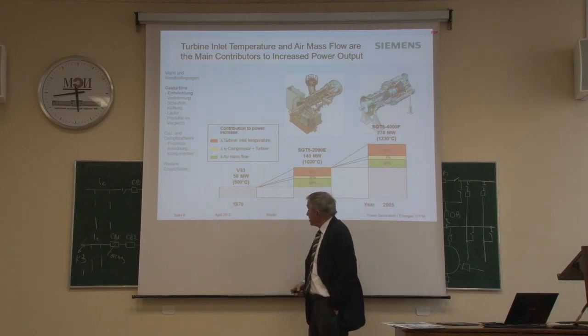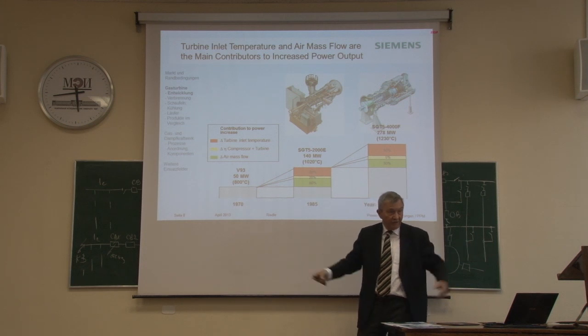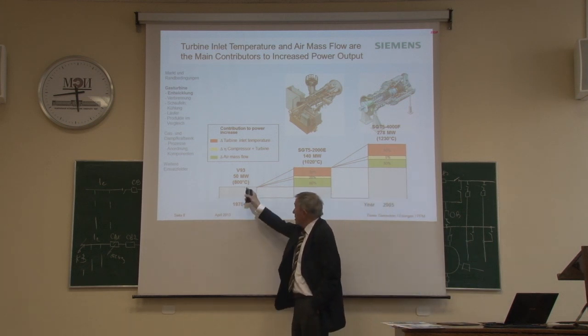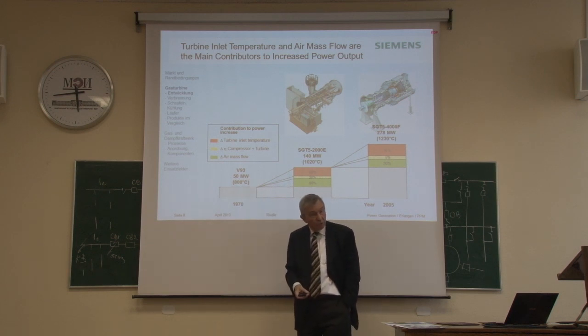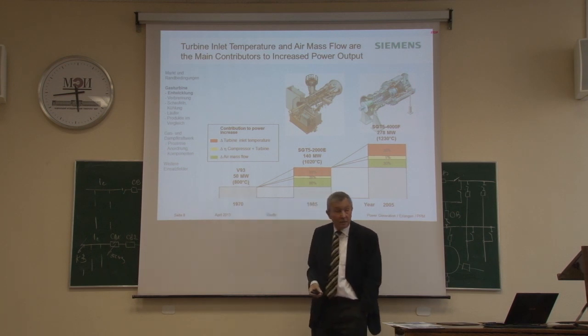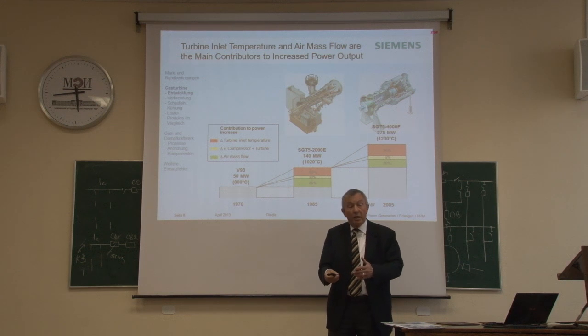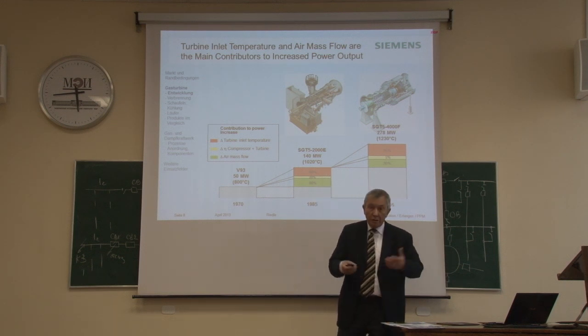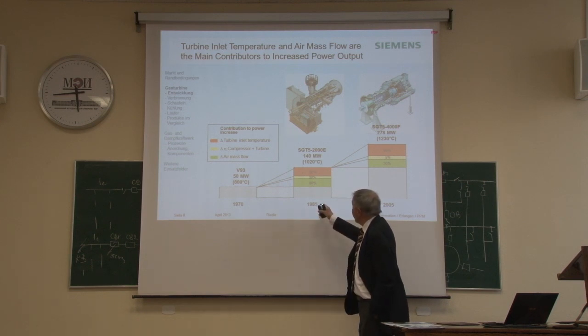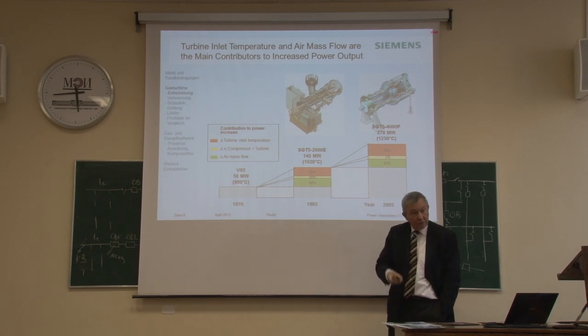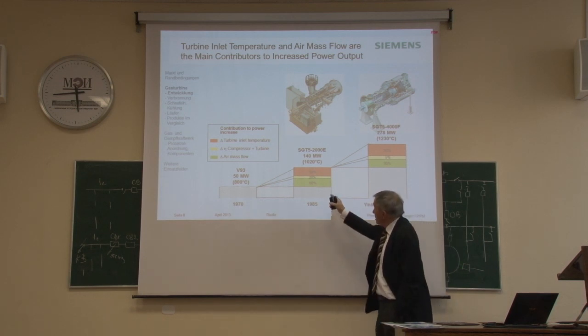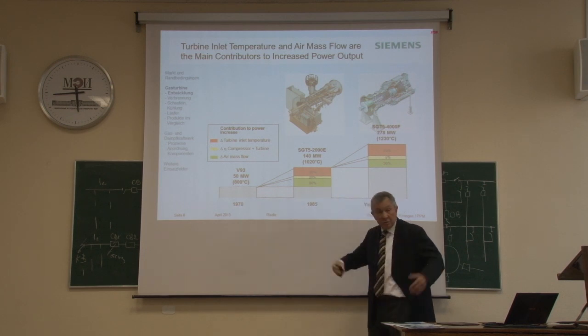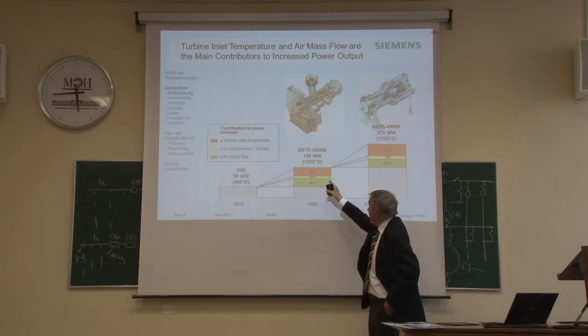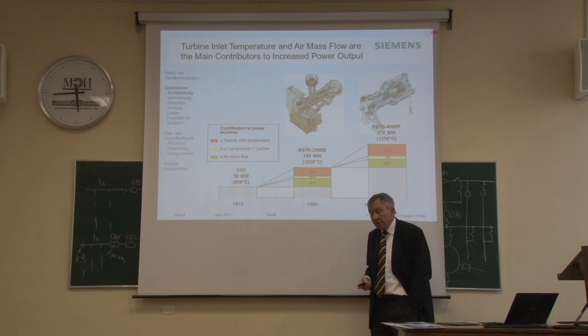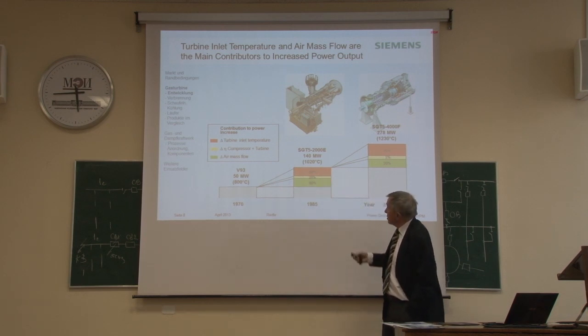When Siemens built their first gas turbines, more or less the same frame as we have for the smaller units today, 1970, that unit had 50 megawatts output, and that ISO temperature was 800 degrees C. And that's a temperature where you still can work with some base alloy. You need no cooling, you need no coating. 85, we raised the temperature by about 220, 250 degrees. And you see the increase in power came from a better compressor, more air pushed through, better efficiency of compressor and turbine, and the remaining, the red part, was due to the increase in inlet temperature.